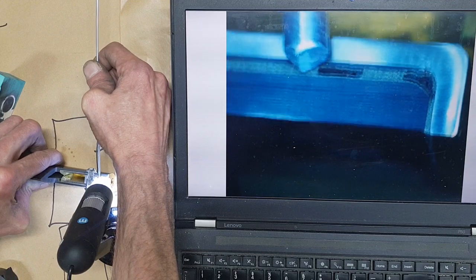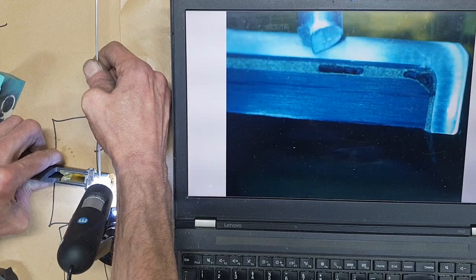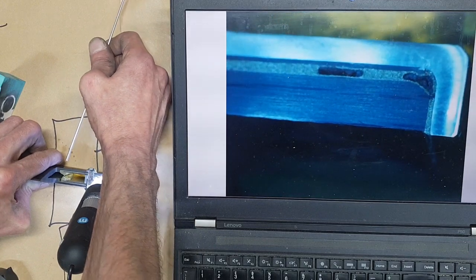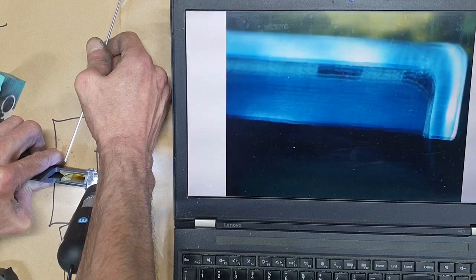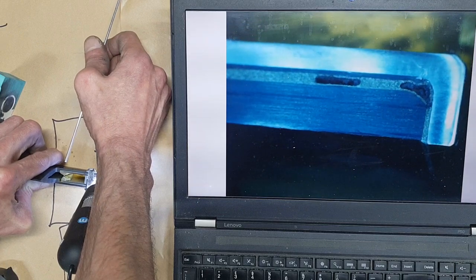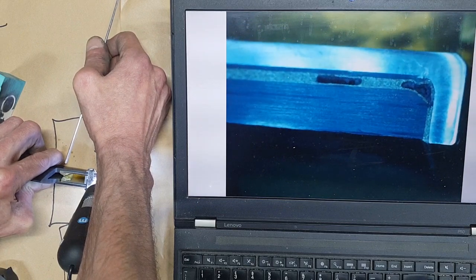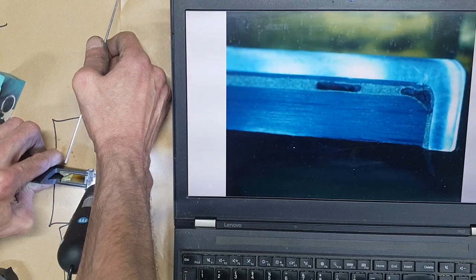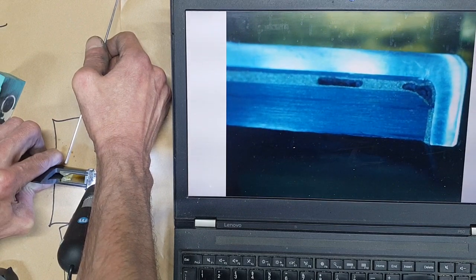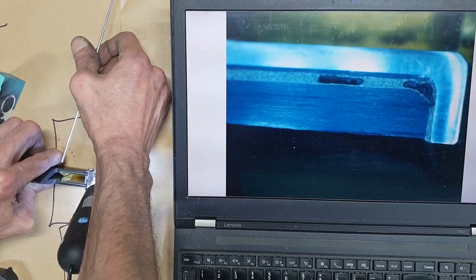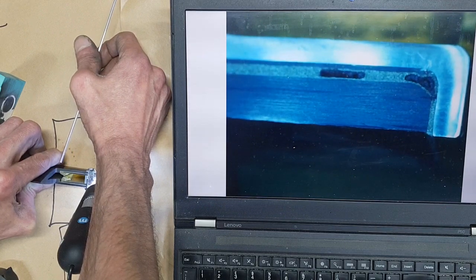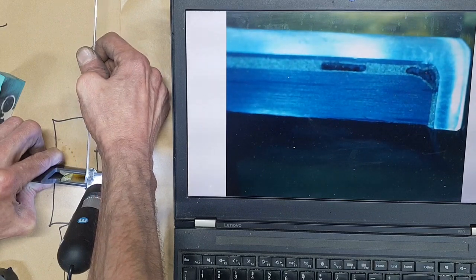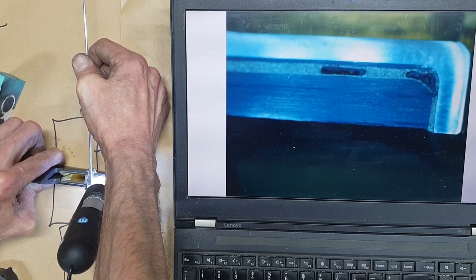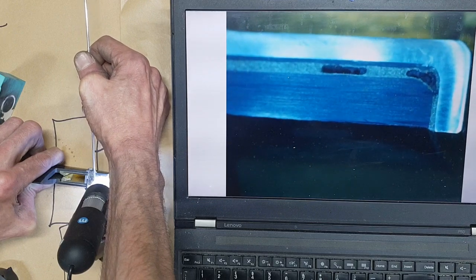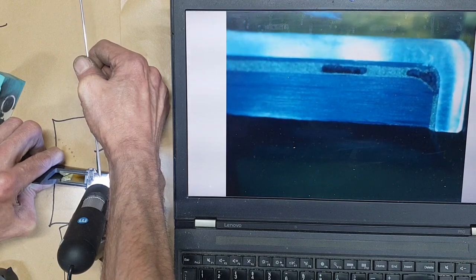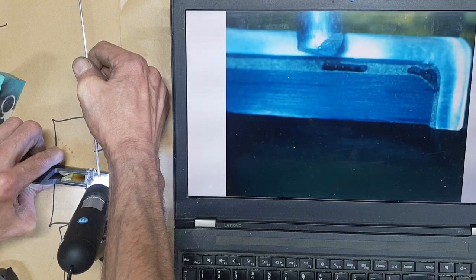There's the epoxy bond line and there's the carbon fiber. This bond line here, if you're bonding either aluminium or titanium to epoxy or to anything else, it's extremely hard to get a proper bond line on the titanium, because titanium and aluminium form an oxide layer which doesn't really grip epoxy too well. So what they do is they cover the part with epoxy. Let's go in there again, which is that black line there.